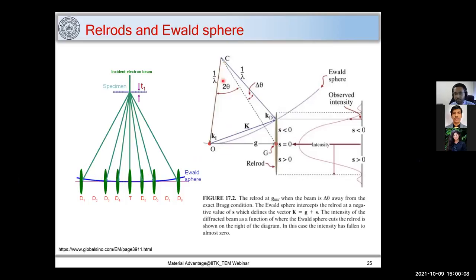Here in this case, I have marked a rel rod here, and here a reciprocal lattice point. And we know that from this point to this point is our G vector, which is a reciprocal lattice vector. And you can see that this Ewald sphere is touching the higher side, or opposite upper side, of this rel rod, where I consider this as a deviation parameter or excitation error. So you can see that this is G, and this is S. This vector is S, and I call it a deviation parameter. Let me write that down also. We'll be looking at it in the coming slide. So this is a deviation parameter, and we'll be seeing why this deviation parameter is so important. So you have been introduced to rel rods and this vector, which is a deviation parameter.